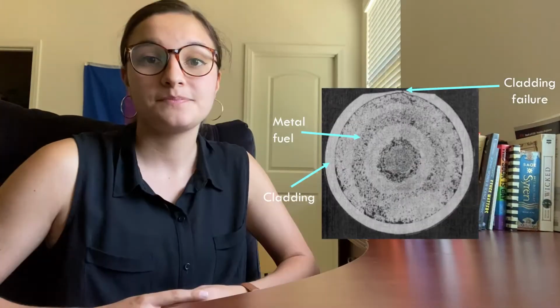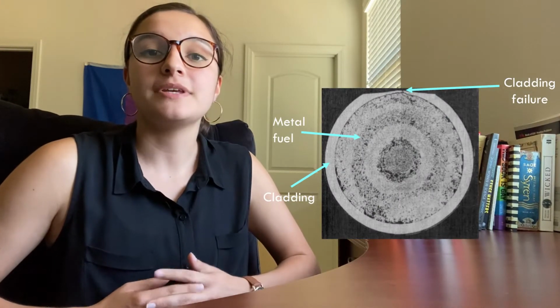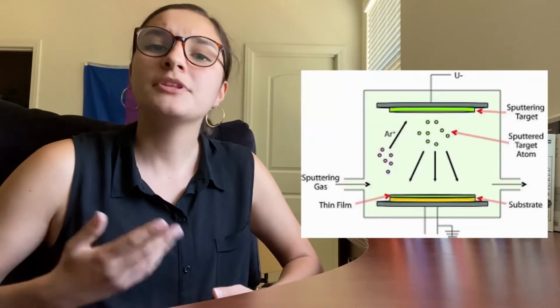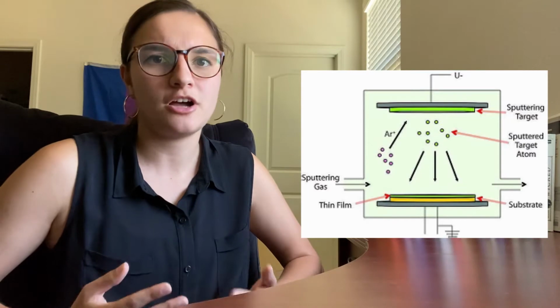An example of a structural material that goes into these reactors is stainless steel, which is often used for cladding. Iron-chromium thin films are being studied by researchers at Los Alamos because they actually serve as a good substitute for studying these stainless steels. And they've been irradiating these thin films and studying how the radiation will impact corrosion and material structure. But the process of growing these thin films is really complicated.